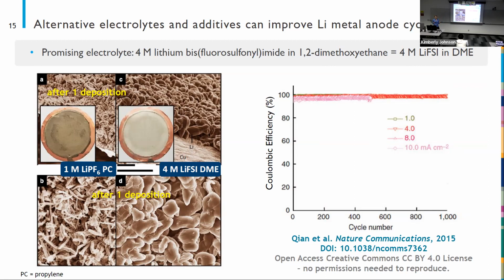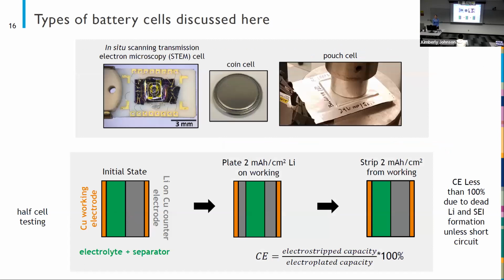And the idea is that you're trying to complex all of the salt with solvent, so you don't have a lot of free solvent lying around that can just react with the lithium. So this is really about coordinating all of the free solvent and stopping that reactivity. So there's a ton of electrolytes now where people have had the same sort of concept of the very high concentration to better control this process. But this is the one that I'll be using throughout my talk. So I wanted to introduce this really nice paper.